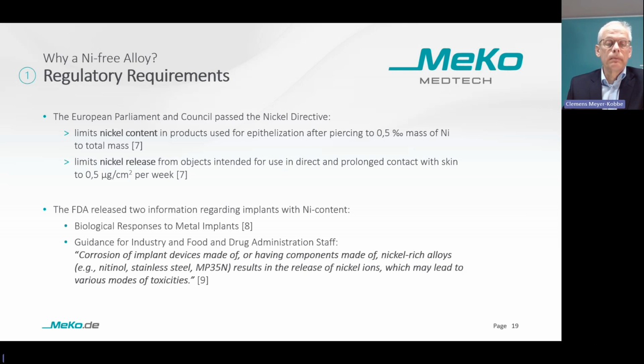Also, the FDA is concerned about devices with nickel content and therefore released 2 pieces of information. One is the biological responses to metal implants, and the other is the guidance on corrosion of implant devices made of nickel-rich alloys, which may lead to various modes of toxicity.